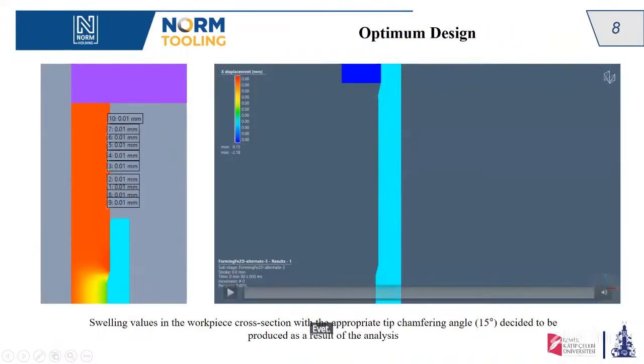As a result of analysis, a 15-degree chamfering angle was determined to be the optimum angle. In this slide, you can see the swelling values in the workpiece cross-section achieved with this optimum design. As observed, this design reduced the swelling in the shaft area to acceptable levels, improving product quality and eliminating the need for subsequent operations. This significantly improved our ability to perform a combined operation in one single die. The animation of the completed 2D simulation is also shown in this figure.